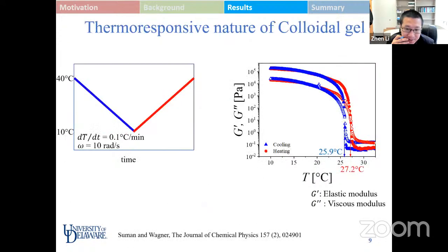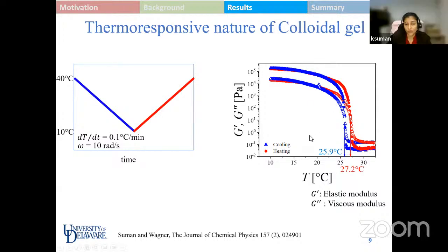So you describe there is a symmetric cooling and heating loading, but the rheology behavior is not quite consistent. Do you know what's the underlying reason to generate this difference, that the cooling and heating curves are different? So the question is why the heating and the cooling curves are different and not on top of each other.